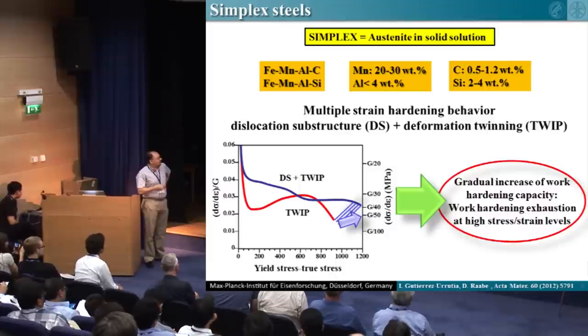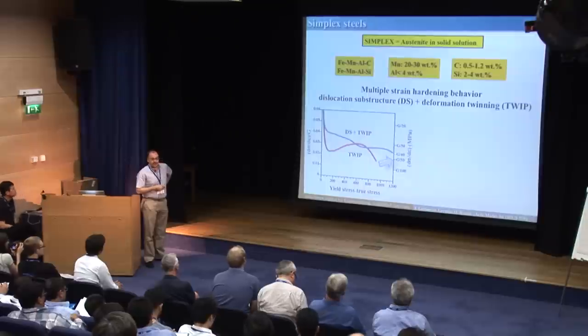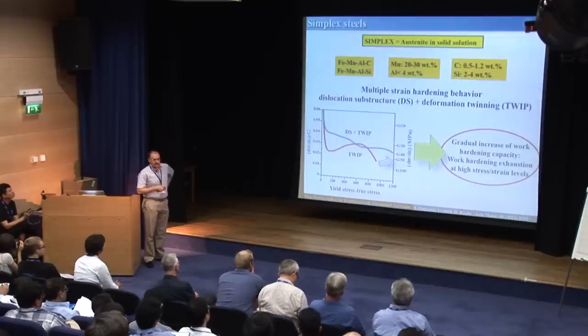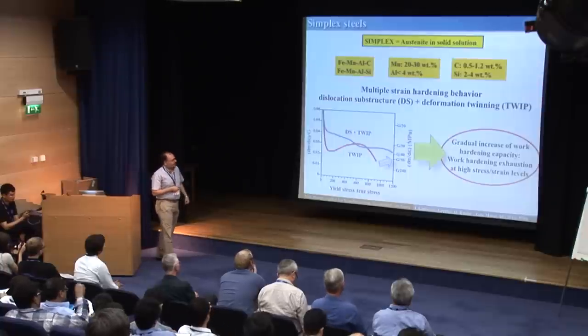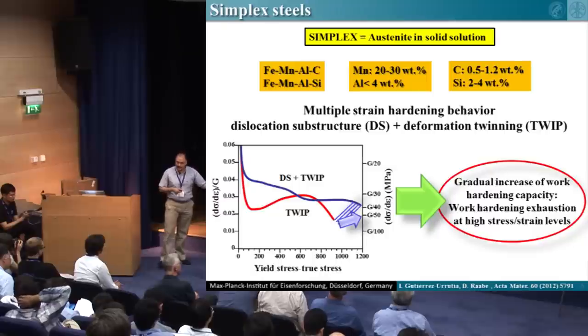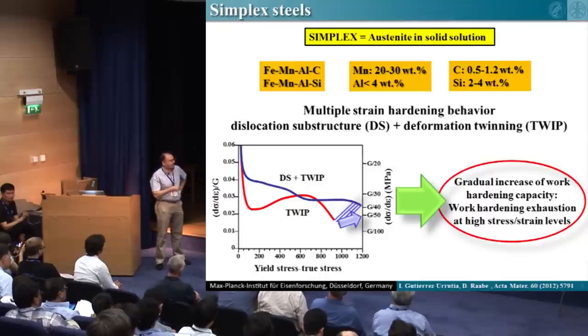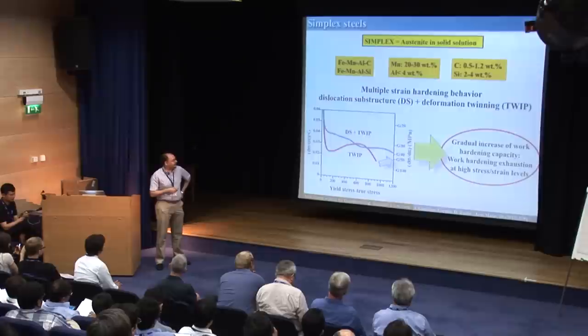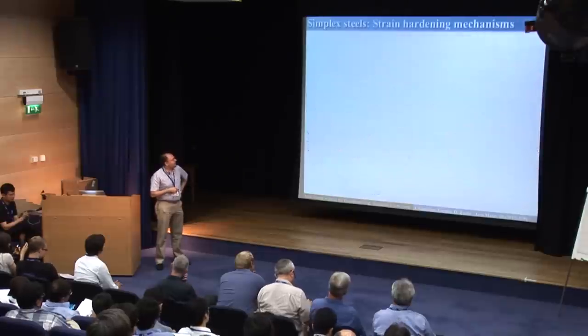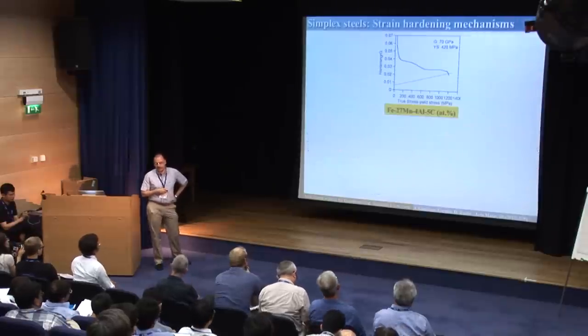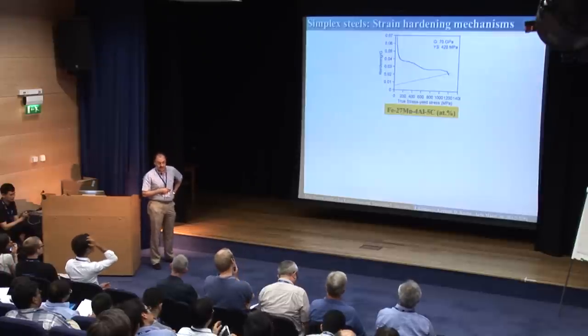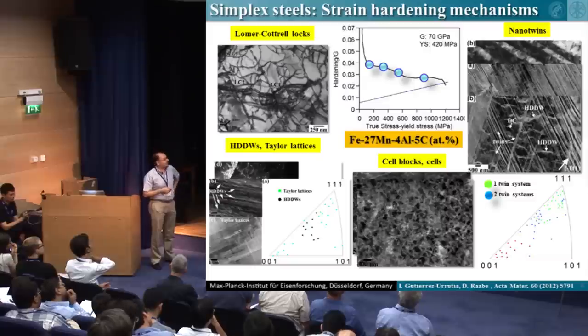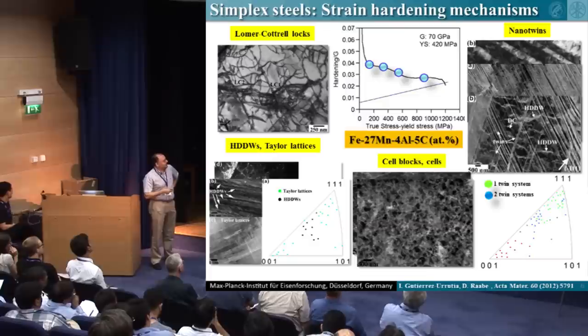And with this, the exhaustion of the strain hardening capacity of the alloy is delayed to higher strain levels. So basically, as a consequence of that, we are not making use of all the power of twinning in terms of strain hardening and microstructure refinement. But first, we refine the microstructure by a dislocation substructure, and later on by twinning. So for that, we need a specific dislocation configuration in order to promote our outstanding strain hardening capacity by dislocation structure. So this is the typical dislocation structure evolution of simplex steel.